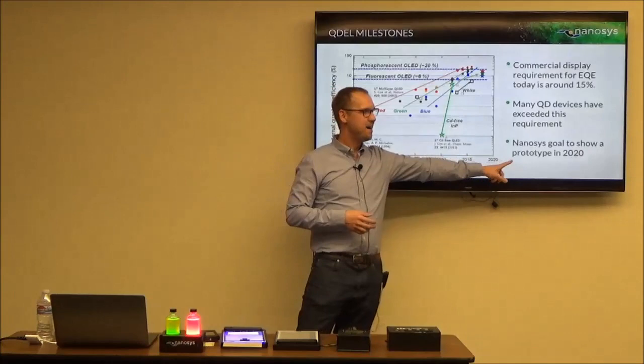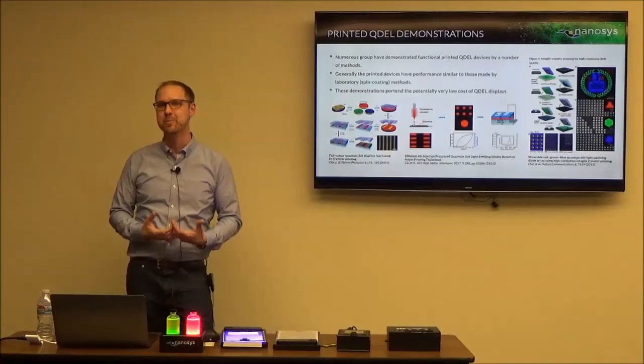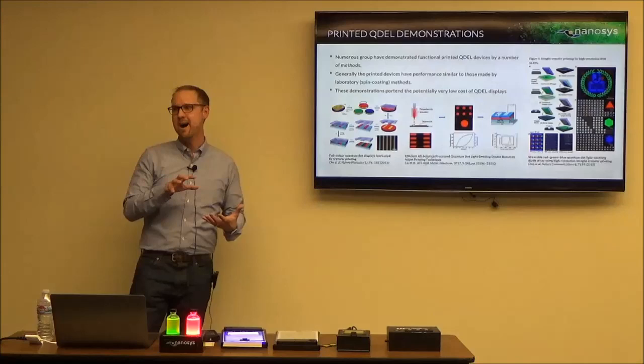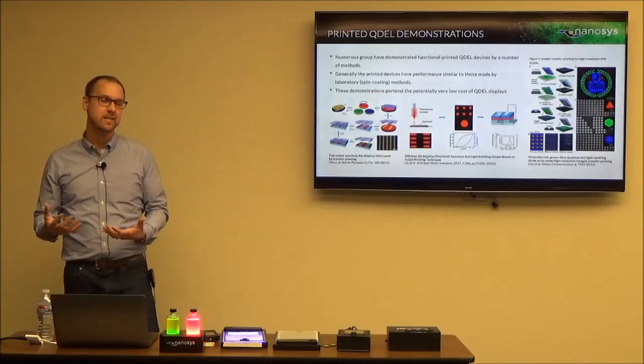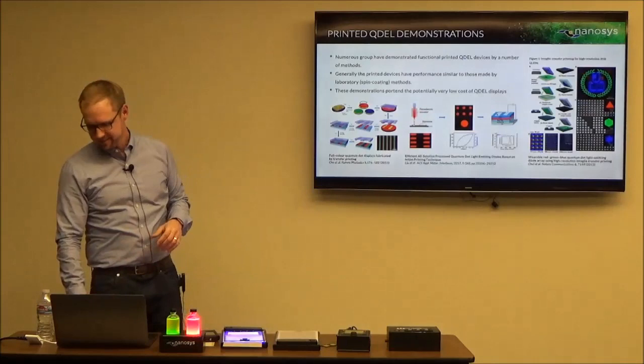We think we'll show maybe a monitor-size display next year with this technology — not a real product yet, but a big step in that direction. It's a really exciting thing for quantum dot technology. Sure, it will have great color, great brightness, and the same contrast ratio everybody loves about emissive displays. But the key benefit is solution processing — quantum dots can be printed in open air, using transfer printing like silkscreening a t-shirt, for very, very low cost displays. OLEDs require vapor deposition under vacuum, a very tough process. Printed quantum dots are what will be really fundamentally disruptive.